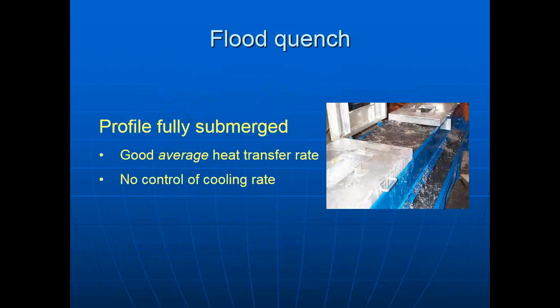Flood quenches have quite a good average heat transfer rate. Their big limitation, and the reason why they have fallen out of favor in the industry, is there is no control of cooling rate or anything else. You put it in the water, it comes out. What you get is what you get. And you have no adjustability. So while they cool quite well, if you're wrestling with geometry, distortion, and such things, you really don't have any tools to address them.